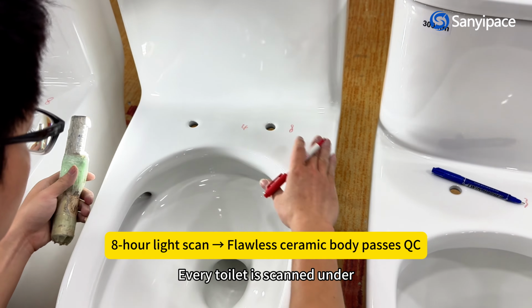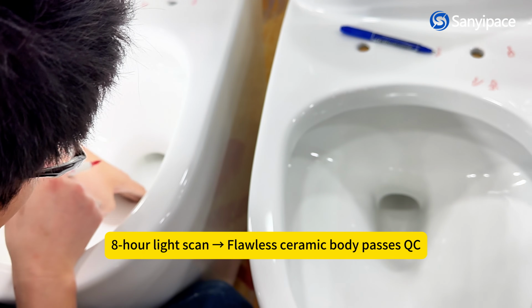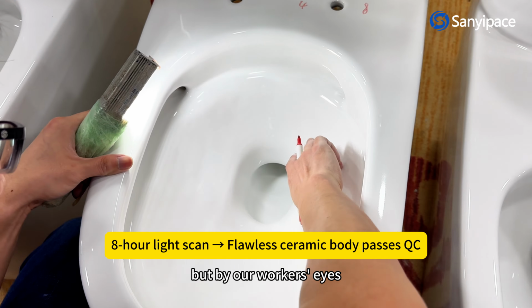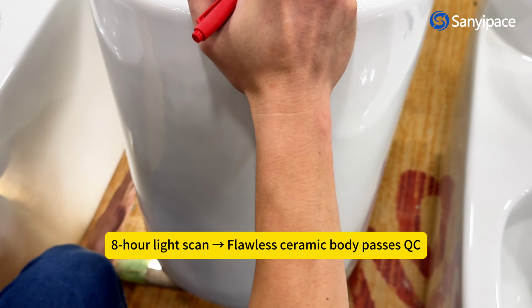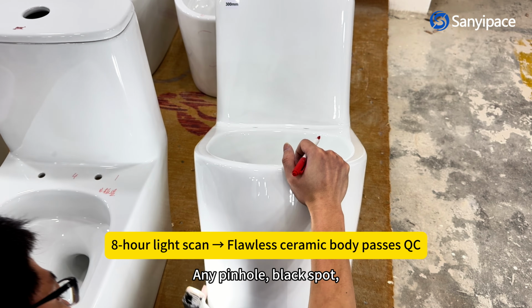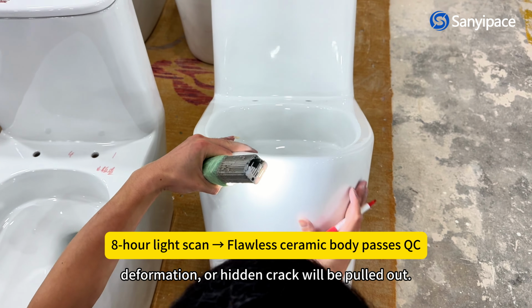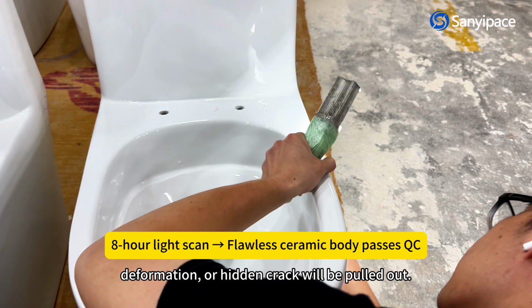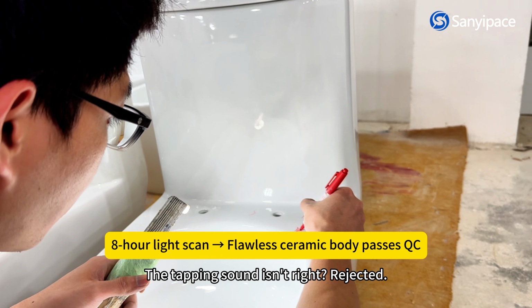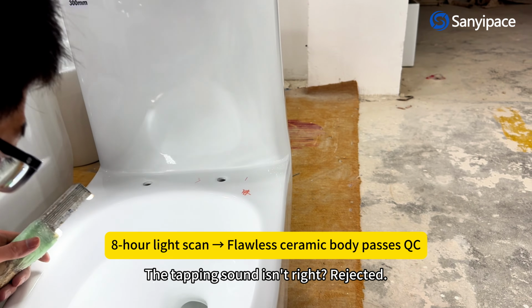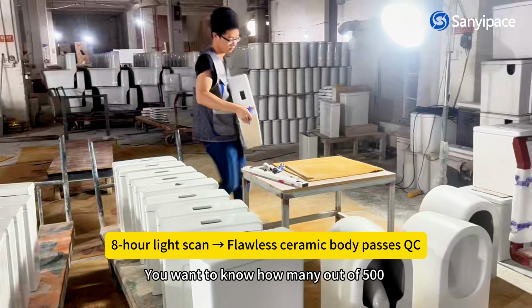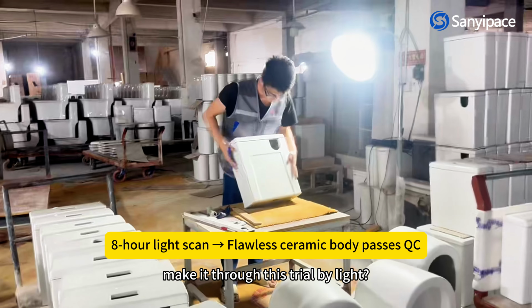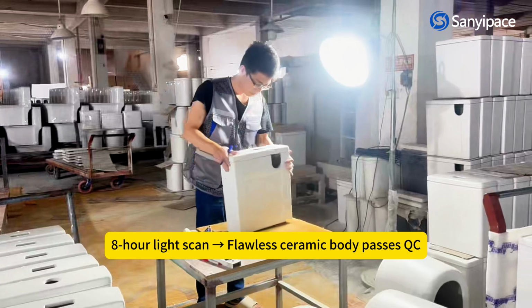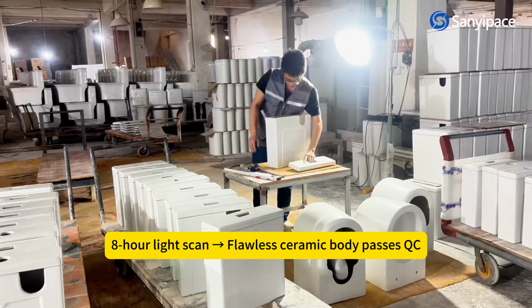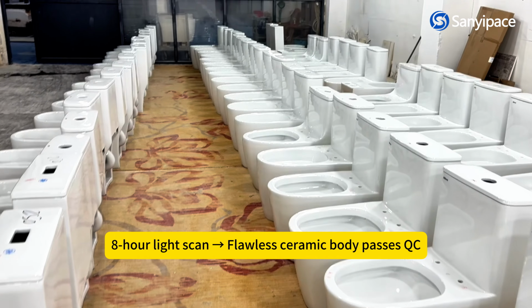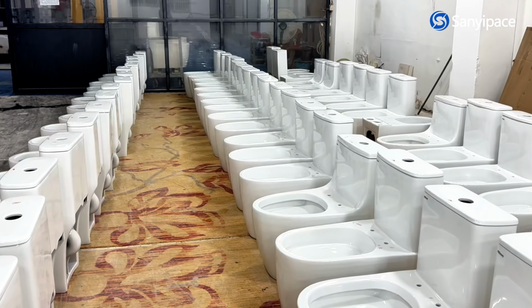Every toilet is scanned under bright lights for 8 full hours, not by a machine, but by our workers' eyes. Any pinhole, black spot, deformation, or hidden crack will be pulled out. The tapping sound isn't right? Rejected. You want to know how many out of 500 make it through this trial by light? We won't give a number, but here's what we can promise. Every toilet that reaches your home has survived this merciless test.